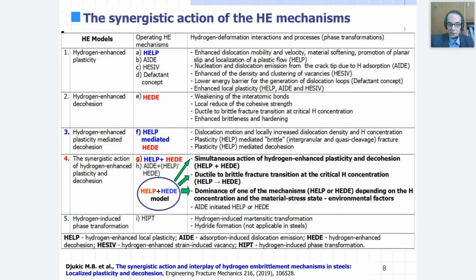Also published in our review paper about hydrogen enhanced plasticity mechanism, HELP, and others about HEDE, and summary that HELP plus HEDE model proposed that simultaneous action of both mechanisms are responsible for hydrogen embrittlement, and the ductile to brittle fracture transition appears at a critical hydrogen concentration, and the dominance of one of the mechanisms mostly depends on the hydrogen concentration in material, marked in red on the previous slide,